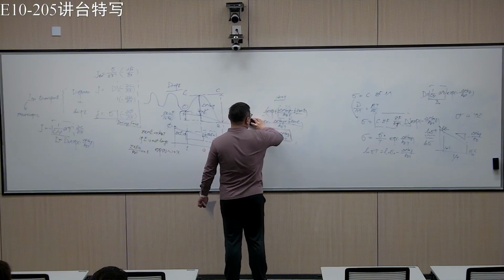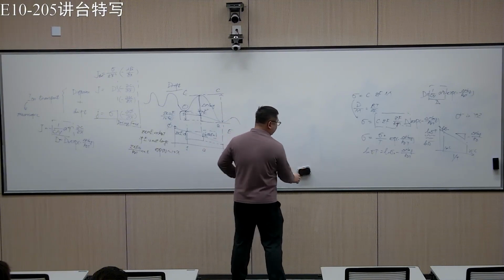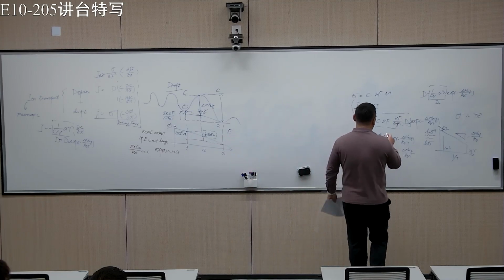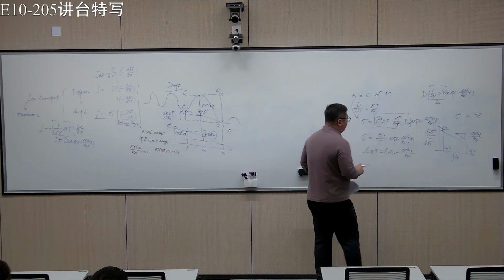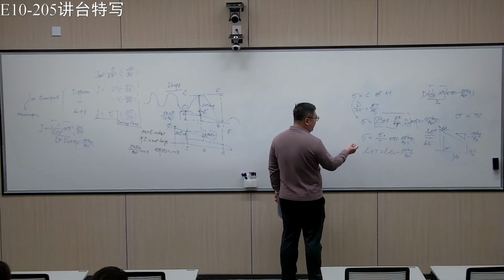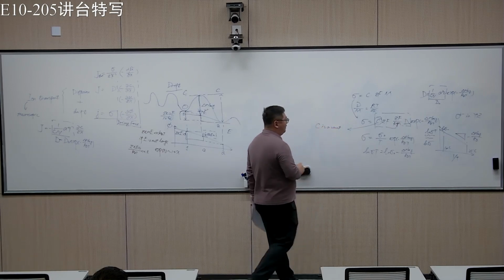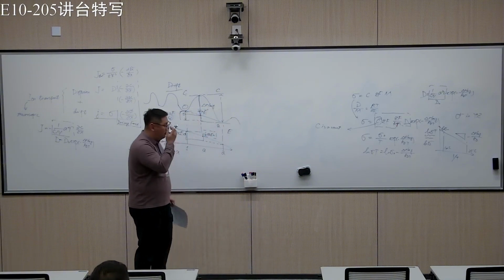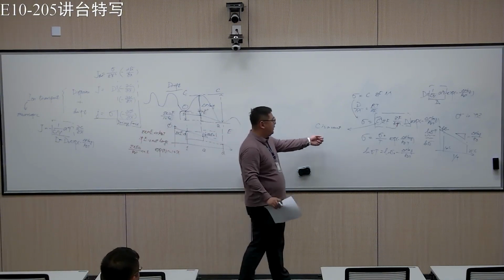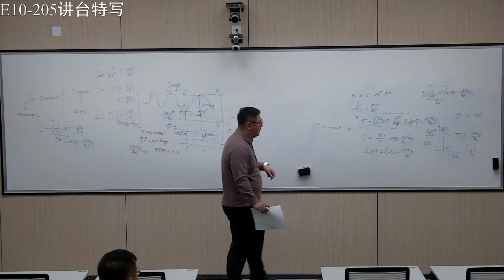One final thing is that you have to be careful because here, for example, the C. The assumption is that the concentration is a constant. So basically, concentration does not change with temperature. You can do this kind of treatment.